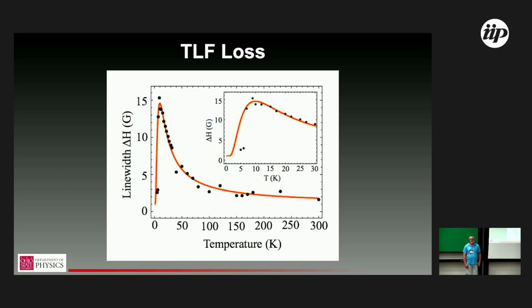So the induced magnon relaxation is proportional to the difference of the population between ground and excited state. When you're at higher temperatures compared to the two-level frequency, this mechanism becomes suppressed. Once you deviate, you start creating this imbalance between ground and excited state, and this reflects on the increase of the line width. If I'm not mistaken, it's a hyperbolic tangent. So you're saying it's proportional to the difference and not the absolute number of available spins. So it's not a phase space argument.